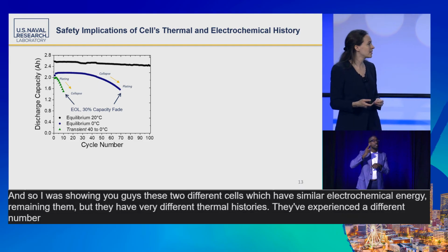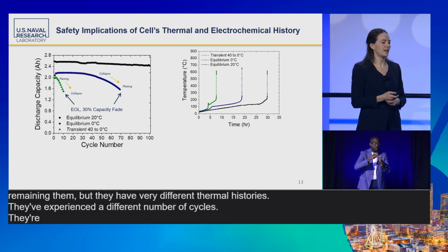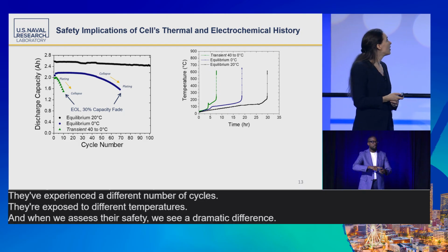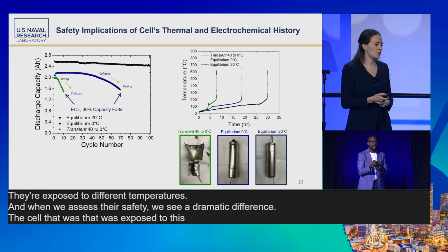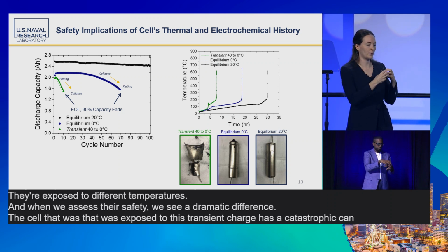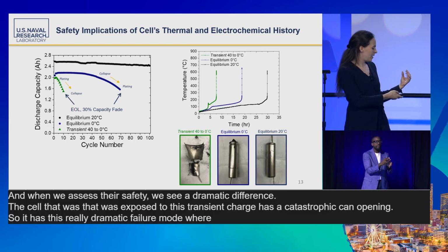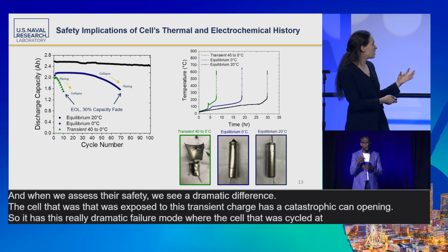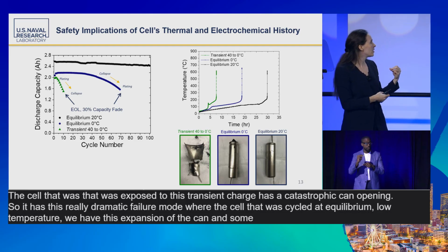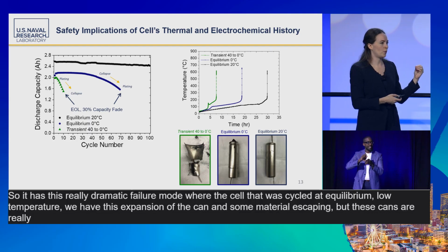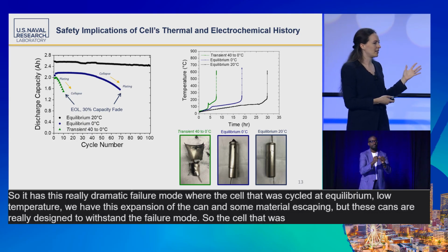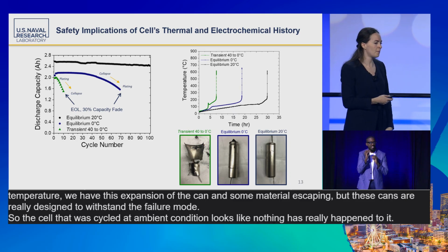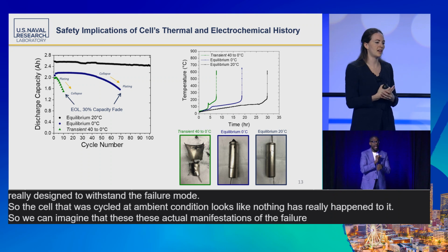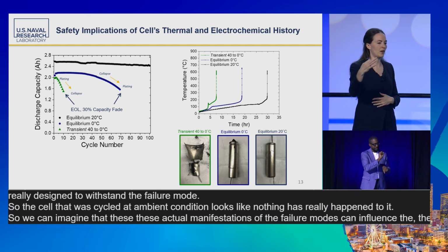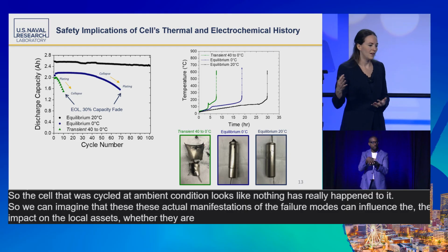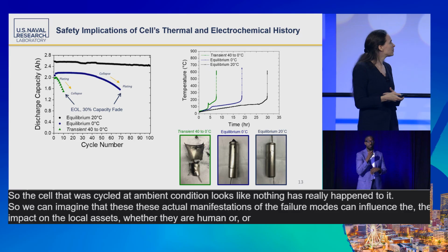They've experienced a different number of cycles, they're exposed to different temperatures, and when we assess their safety, we see a dramatic difference. The cell that was exposed to this transient charge has a catastrophic can opening. So it has this really dramatic failure mode, whereas for the cell that was cycled at equilibrium low temperature, we have this expansion of the can and some material escaping. But these cans are really designed to withstand the failure mode. So the cell that was cycled at ambient condition looks like nothing has really happened to it. We can imagine that these actual manifestations of the failure modes can influence the impact on the local assets, whether they are human or in value.